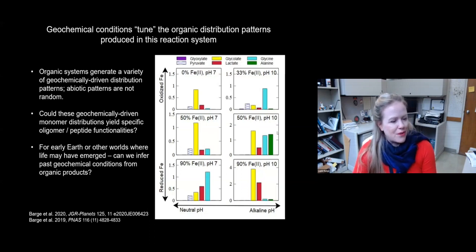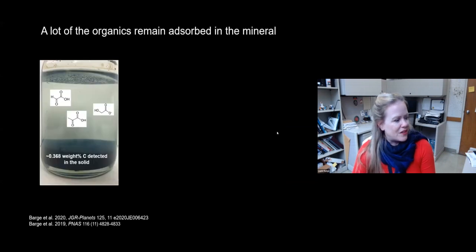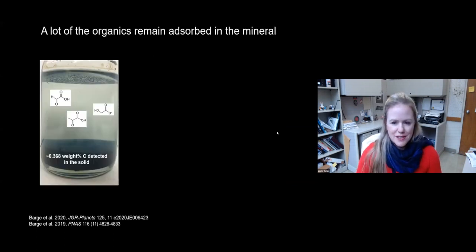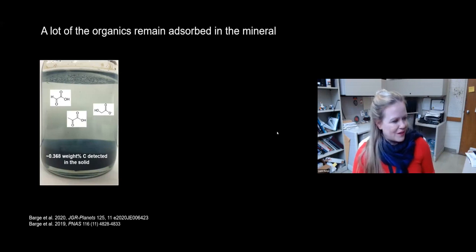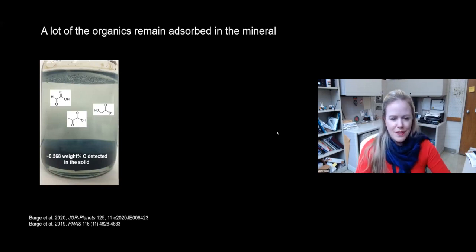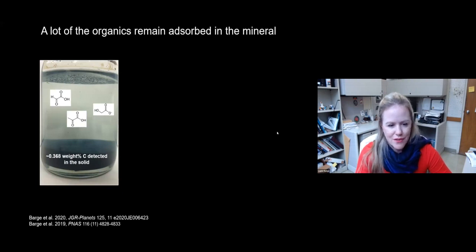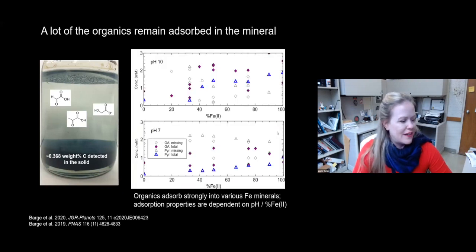The other thing that we looked at is what actually happens to these organics. So remember, this is all from samples of the liquid. And we did also observe that a lot of the organics in this experiment stay adsorbed in the mineral. So we did a combustion analysis of this mineral phase, and we detected about 0.36 weight percent carbon in the solid. And if you back that out to what we put in initially, this is for a pyruvate experiment, we found that about half of the organics that we added in the first place are now stuck in the mineral. And then you can also just add up all of the detected organics in the liquid, subtract from what you put in, and then the difference is what must be in the mineral.